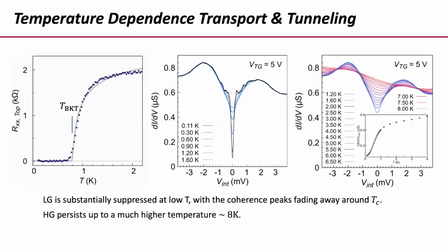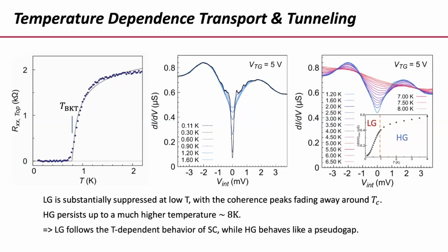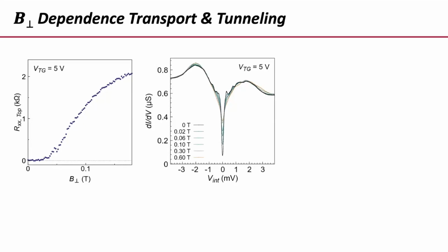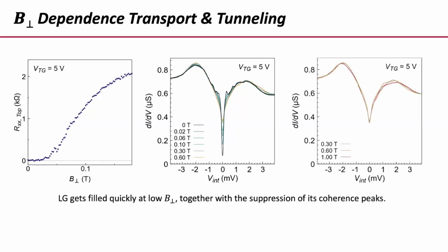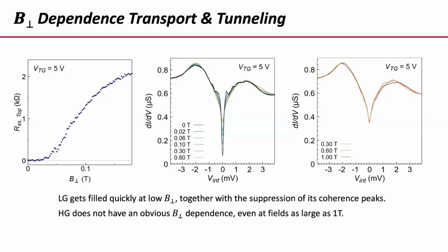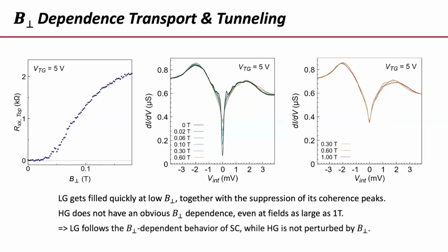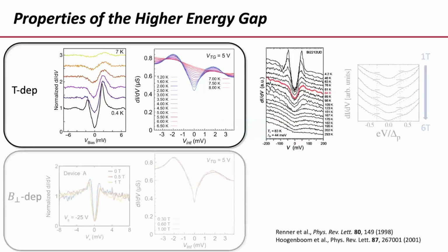And you can characterize that by rapid evolution of the low energy gap and very weak evolution with temperature of the high energy gap. This high energy gap, in fact, behaves like a pseudogap, okay? While the low energy gap behaves like a superconducting gap. You can do the same thing with tunneling and perpendicular magnetic field. This inner gap evolves very fast, whereas the high energy gap barely changes with magnetic field up to pretty high energies. Again, this is consistent with the pseudogap behavior, whereas this is the superconducting gap.